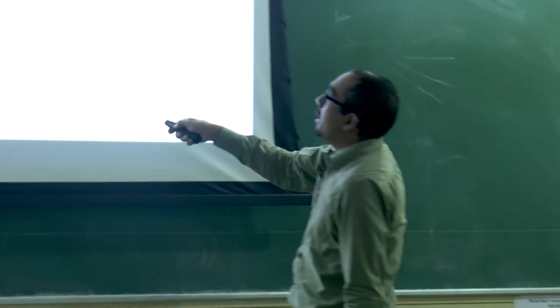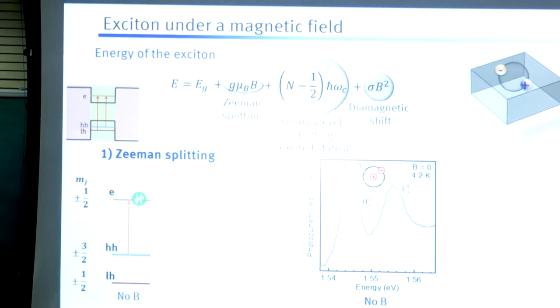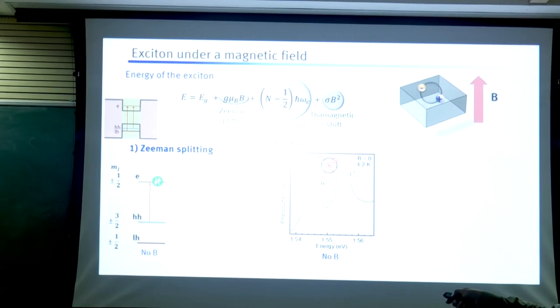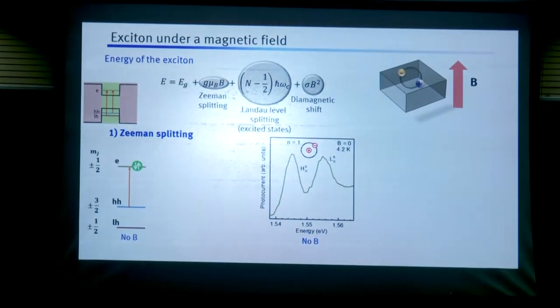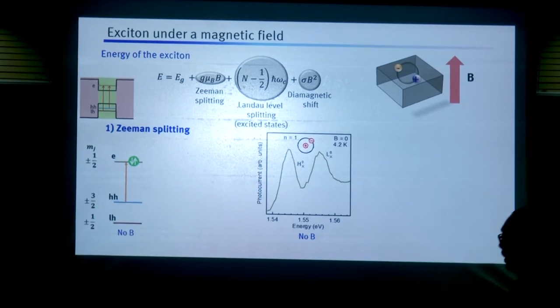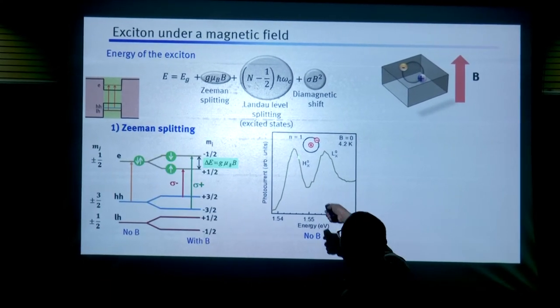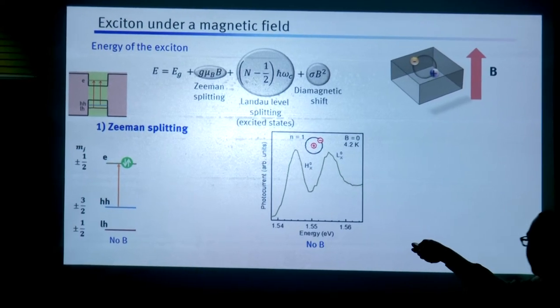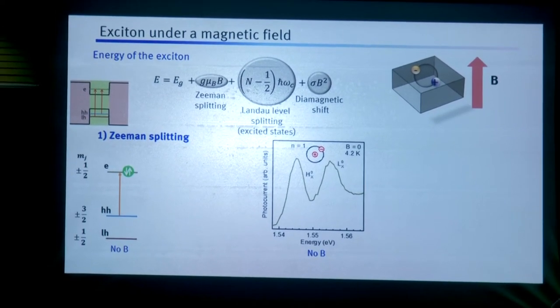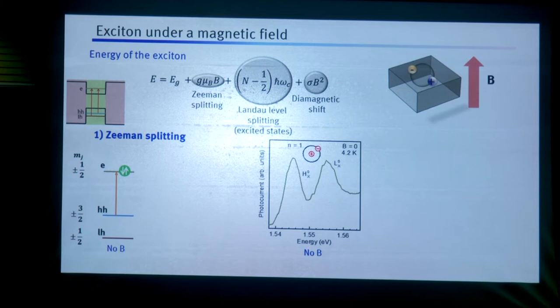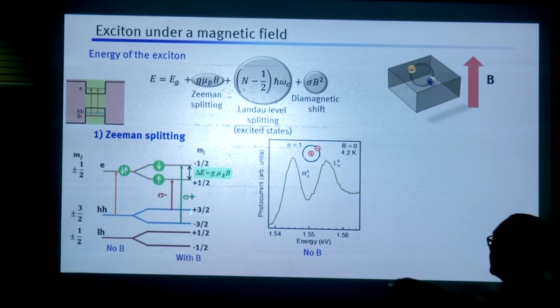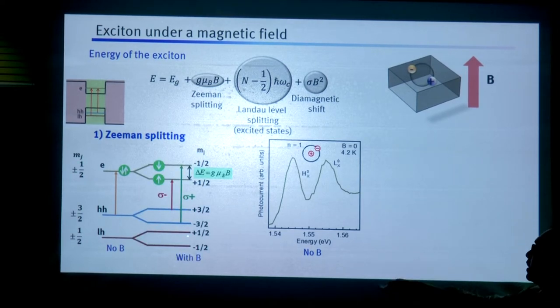First is Zeeman splitting. Let's suppose you have these spectral lines of the excitons in a quantum well, in the absence of magnetic field. So then these transitions, for example, this hole to electron transition is taking place, and this is doubly degenerate. So essentially, if you make circular polarization resolved spectroscopy of this, the 2 spectra will look exactly the same, because they are degenerate. But once you apply magnetic field, the degeneracy is lifted, and now sigma negative and sigma positive, meaning 2 degrees of circular polarization, are at different energies.